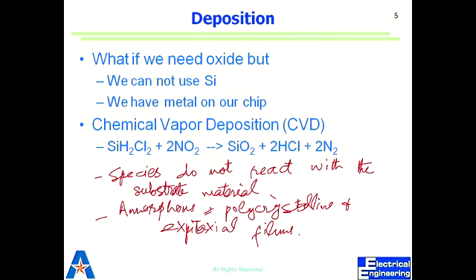In any case, this is the basic idea of deposition, that you want to deposit material from outside. There is a long list of materials that can be deposited. What defines the deposition is that some materials stick well on others, some don't. So we may want to use sticky layers, a material that will bind, adhere to both of those materials that don't bind to each other. A very common example is titanium and gold, or chrome. They stick well to silicon dioxide, but gold doesn't stick directly to silicon dioxide or silicon. So we use a thin layer of titanium or chrome as an adhesion layer, a sticky layer, to put our gold on top of that.